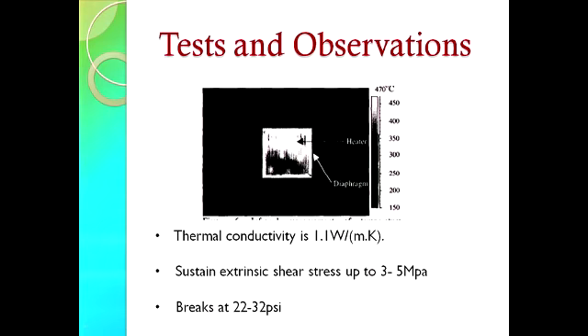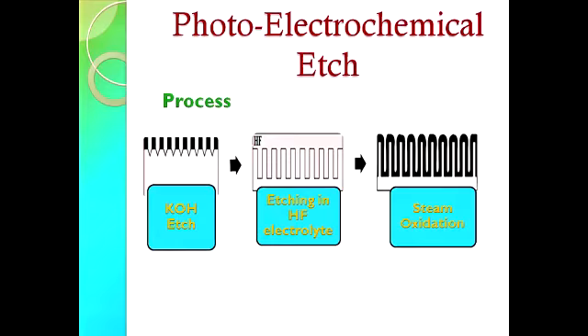And it can sustain extrinsic shear stress up to 3 to 5 megapascals. And it breaks only at 22 to 32 psi. So this is a good insulating material.